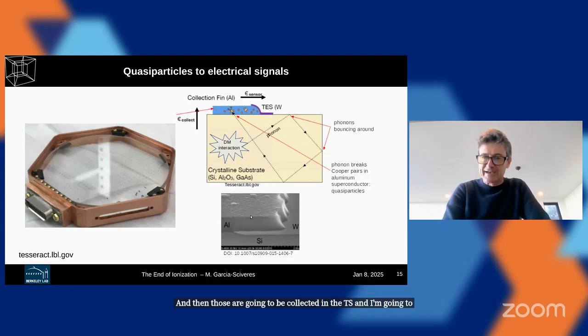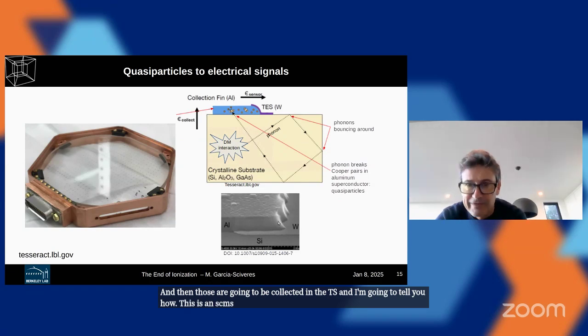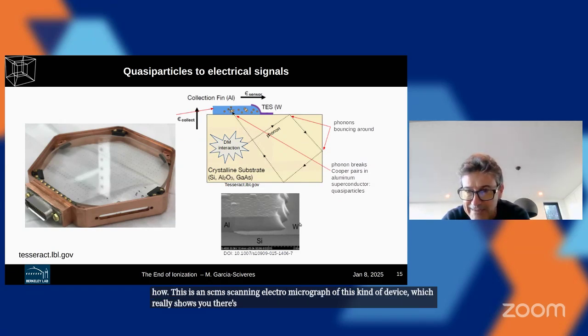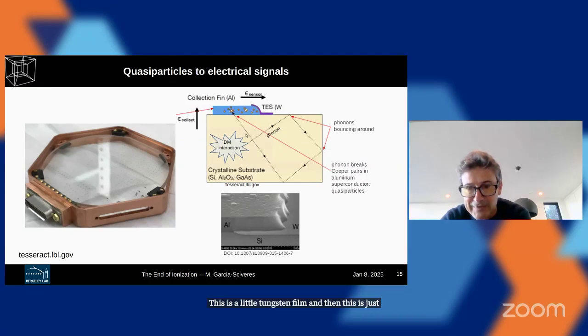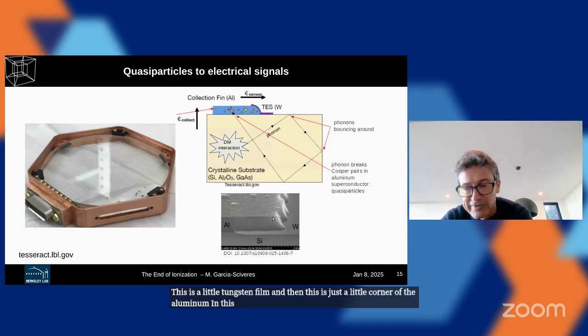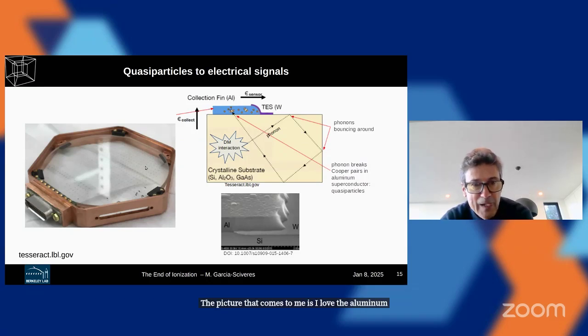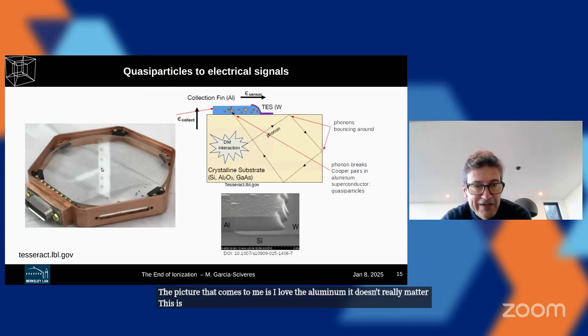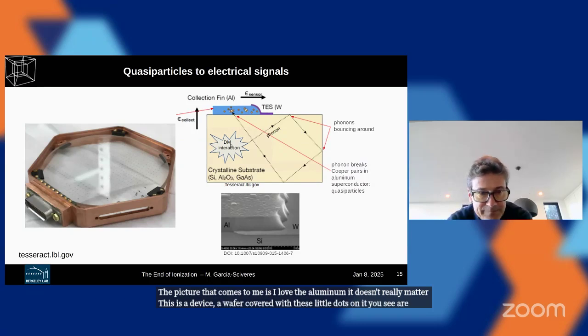And this is an SEM, scanning electron micrograph, of this kind of device, which really shows you there's a lot more aluminum than tungsten. This is a little tungsten film, and then this is just a little corner of the aluminum here. In this case, the tungsten is below the aluminum. In the picture, the tungsten is above the aluminum. It doesn't really matter. This is a device, a wafer covered with these little dots on it. You see these things.